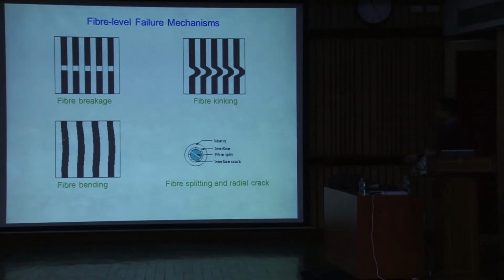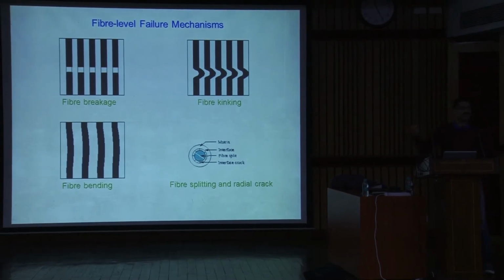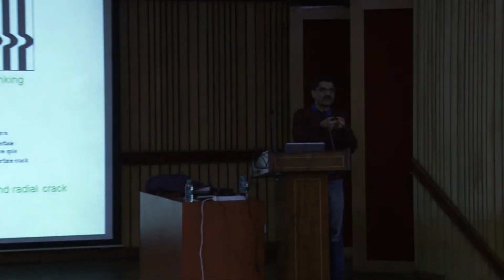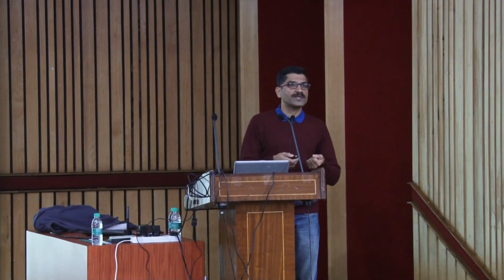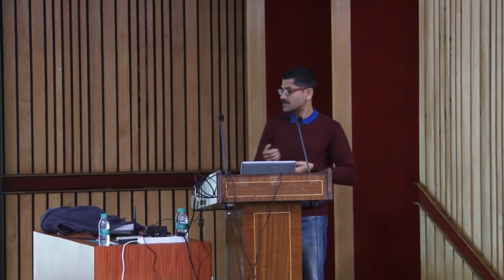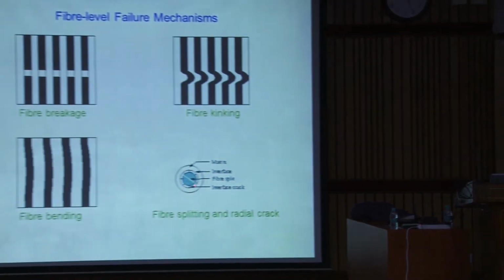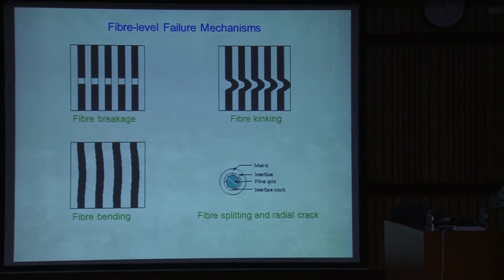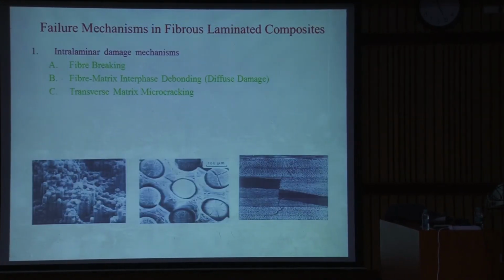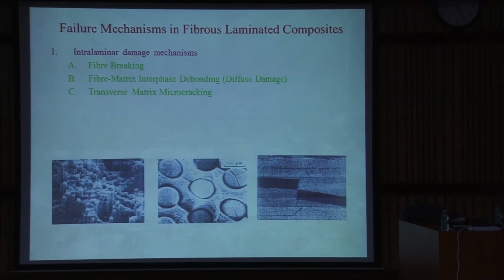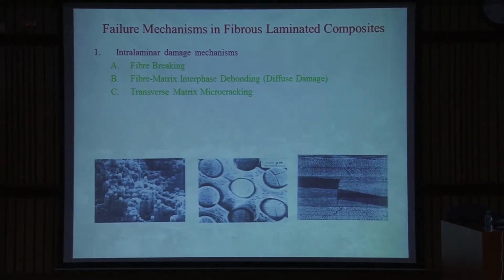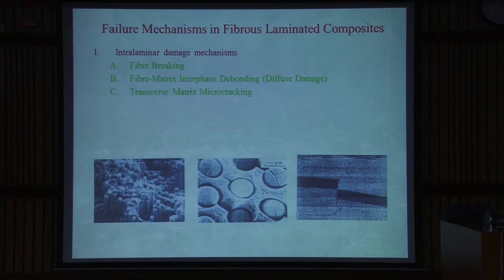Another mode of failure is fiber bending. These are long fibers. When you are putting them in the matrix material, or when you are making the composite material, it is possible that you are not stretching them sufficiently, and so when they are cured along with the matrix material, there is a bending in the fiber. One more level of fiber failure is fiber splitting and radial crack. Maybe I can go to the previous picture. As you can see here, this is the fiber, split along the radial directions. Here it is split in two halves, whereas you see that radial cracks develop into this.